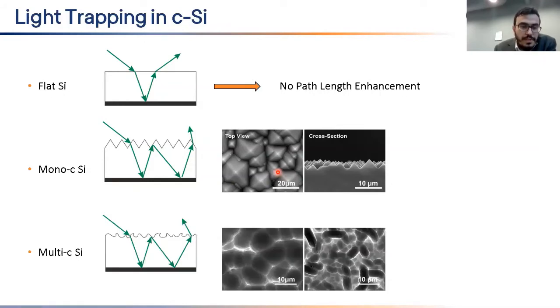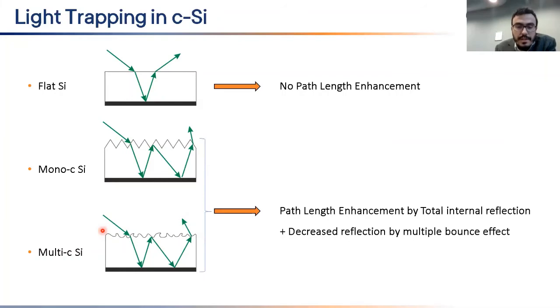And also for multicrystalline silicon solar cells, since you don't have a definite crystal structure, you cannot make pyramid surface texturing, but you can make isotextures, which are some random microstructures on the surface of multicrystalline silicon solar cells that enhance light trapping. So this path length enhancement by total internal reflection and decreased reflection by multiple bounces effect increases the solar cell efficiency.